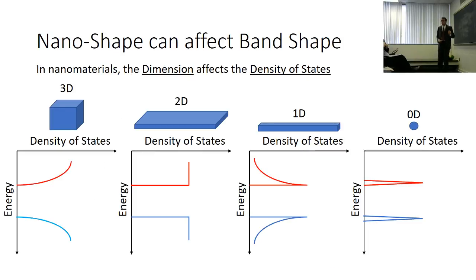Besides nano size, the shape also affects things. Before I showed a density of states versus energy for a 3D material. There are also changes when you go to a 2D, 1D, and 0D material — nanosheet, nanowire or nanotube, nanoparticle. A nanosheet looks very similar — these are step functions, imagine changing the size of the rungs on your ladder. These are still pretty fat rungs — you absorb things above an energy band gap, and you still get the benefits of a 2D material. Typically 2D materials are more reactive and have higher surface areas.